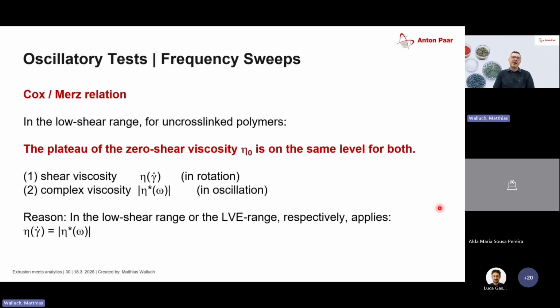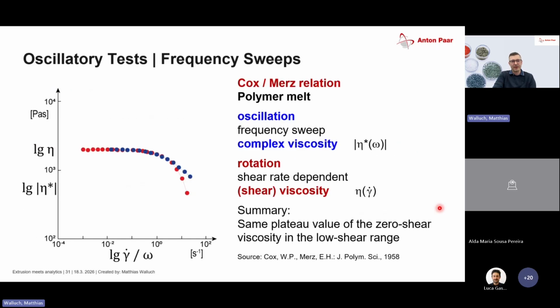I told you about frequency sweeps and about shear rheology, and I also already said that you can compare shear viscosity and complex viscosity. This is because of the Cox-Merz rule, or relationship, which allows for uncross-linked polymers to basically say shear viscosity equals complex viscosity. So we can translate one measurement to the other. Is this really true? We can have a look.